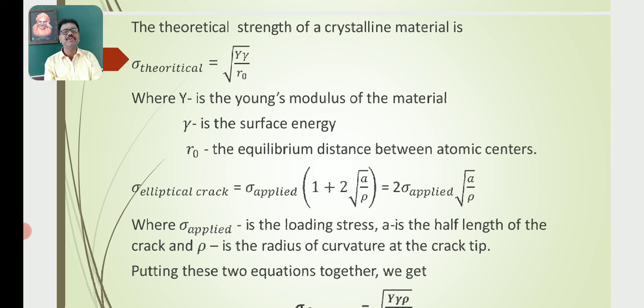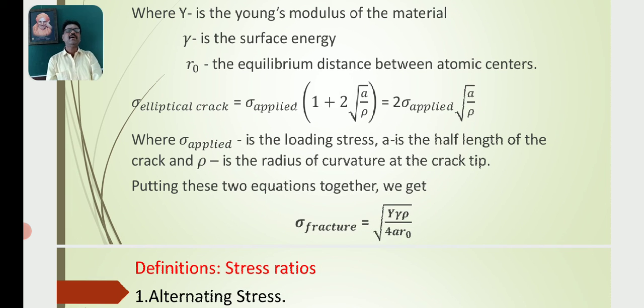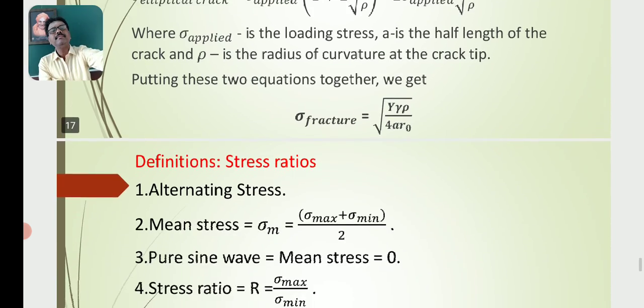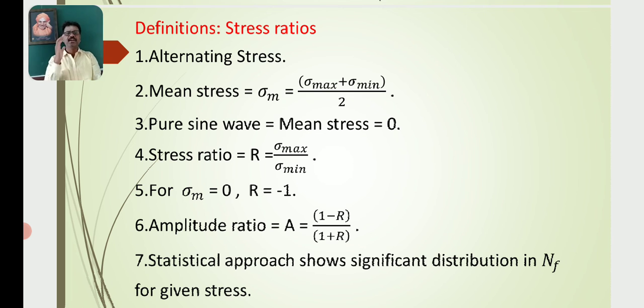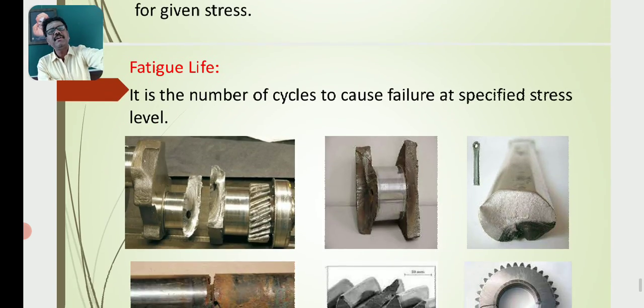Putting these two equations together, we get sigma fracture, which is equal to root of Y gamma rho by 4a r naught. Here are some definitions related to fatigue fractures. Mean stress, sigma m, is equal to sigma maximum plus sigma minimum by 2. For a pure sine wave, the mean stress is equal to 0. Stress ratio R is equal to sigma minimum by sigma maximum. For sigma m equal to 0, R is equal to -1. Amplitude ratio A is equal to 1 minus R by 1 plus R. A statistical approach shows significant distribution in NF for a given stress. So these are some of the concepts for fatigue.